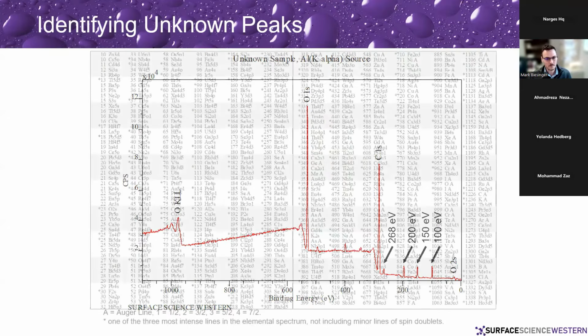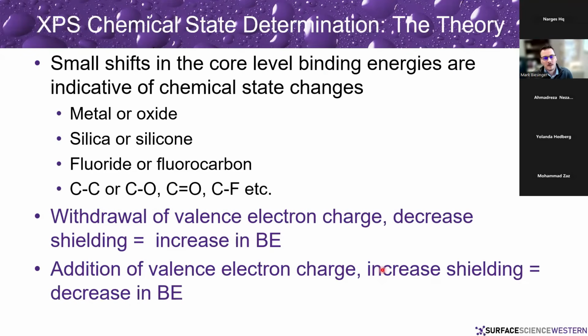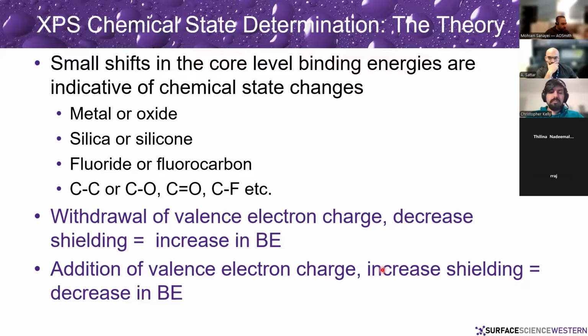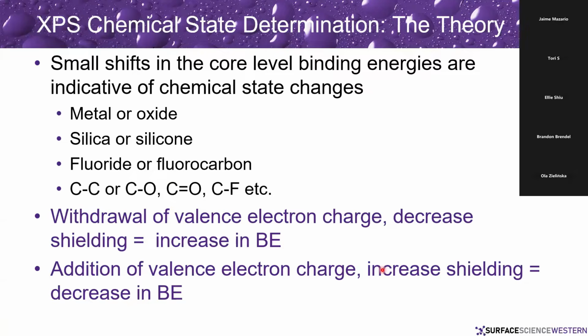Chemical state determination. In theory, small shifts in the core level binding energies are indicative of metals or chemical state changes. So whether you have the metal or oxide, silica versus the silicone, fluoride versus fluorocarbon, etc. As you withdraw valence electron charge, you decrease shielding and increase the binding energy that you get. As you add valence electron charge, increase shielding, you see a decrease in binding energy of those core electrons.